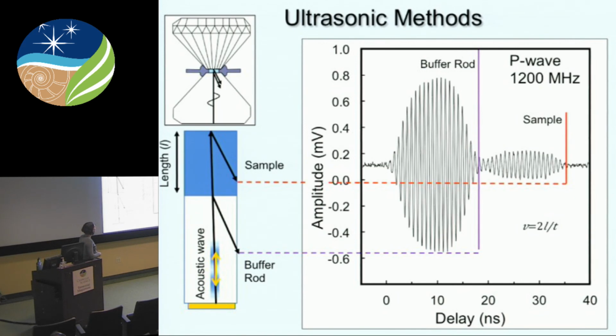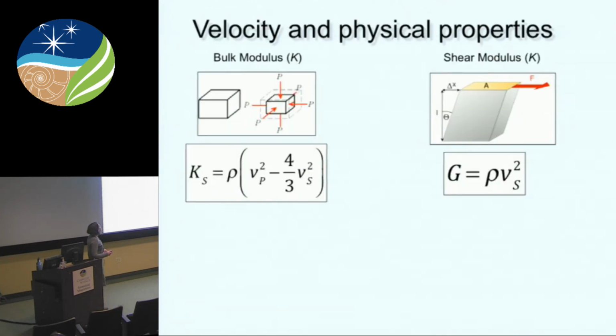And it works fundamentally the same, just instead of having the buffer rod connected directly to the sample, we have a diamond cell that acts as an extension of the buffer rod. And so we're looking for the signal between the diamond return and the far side of the sample. So velocities give us information about physical properties like the bulk and shear moduli. These are the things that seismic waves are sensitive to.